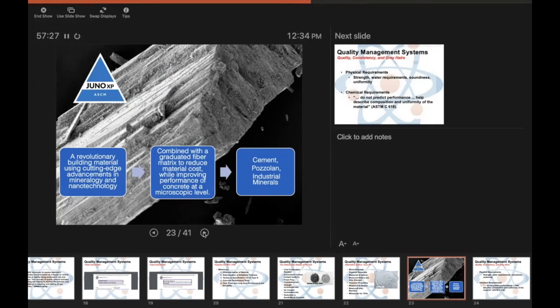It has a fibro-like morphology and a toughness greater than para-aramid fibers, greater than Kevlar. It has a similar chemical makeup to the calcium silicate hydrate, and what we think is happening is that we're getting not only mechanical bonding between that mineral component, but we're also getting chemical bonding.